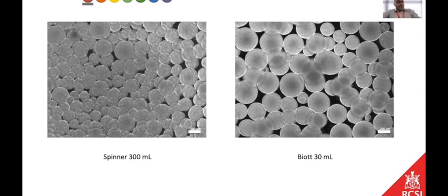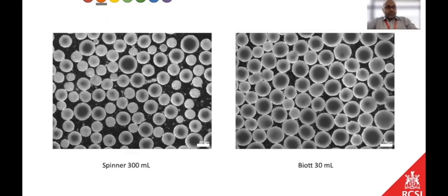On the left side, you see the 300 ml flask cultures, and on the right side, you see the 30 ml flask. Now, this is a pluripotent stem cell stage. So this is basically when we adopt our 2D cell culture into a 3D cluster formation. These are round, spherical, like spheroids or embryoid bodies, but not really like those. These are just a cluster of pluripotent stem cells, which is between 200 to 300 microns in diameter. And they have this kind of a shape. So you can see that they are there.